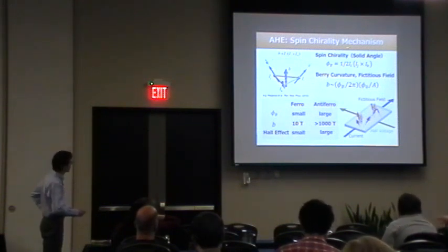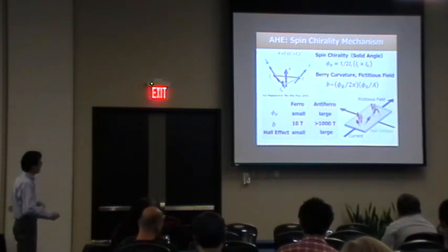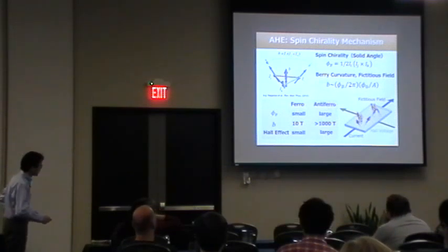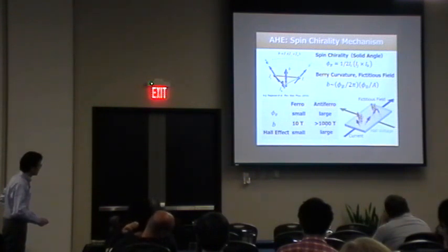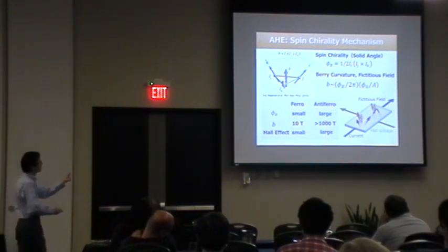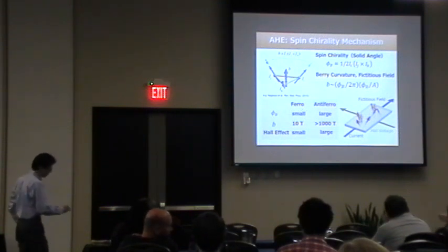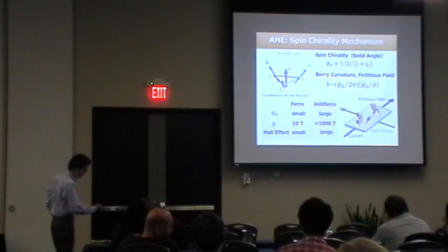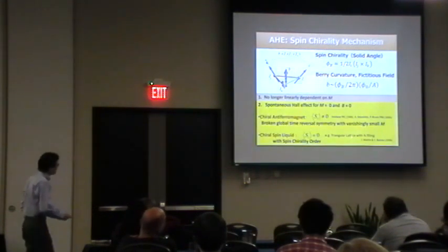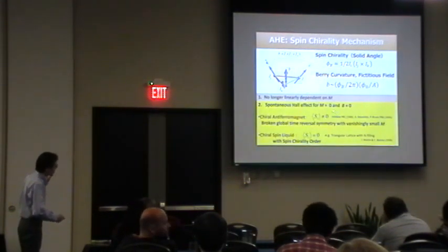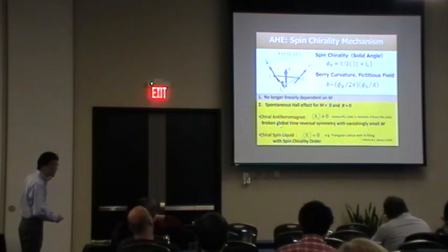That is what this recent theory suggests. So if you follow this mechanism, if this is the case, anti-ferromagnet actually is a better place to look for the anomalous Hall effect. The solid angle vanishes to zero for ferromagnet, but it can become large in anti-ferromagnet. And the fictitious field can be as large as 1,000 Tesla. Okay? So theoretically, even under zero magnetization and zero field,